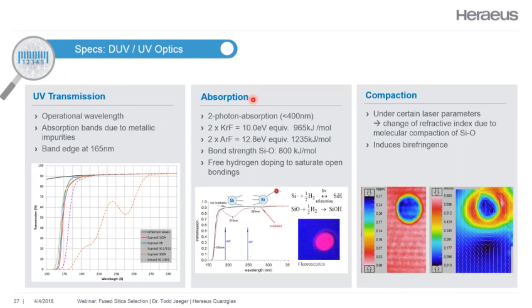Now, when we talk about absorption, when we looked at infrared, we were really considering not only some absorption by the metallic impurities, but primarily the absorption due to the OH content. In the UV, we're more concerned about not single photon absorption, but a 2-photon absorption process that can occur. With either your krypton fluoride or argon fluoride, if you have a 2-photon absorption event that occurs, you've got enough energy within the system to break the silicon oxide bond. When this happens, you can form color centers within the material, and this is when your solarization can occur. It also can cause defects that then would have fluorescence. If you have some free hydrogen within the material, this actually will saturate these open bonds and give you sort of a self-healing material.